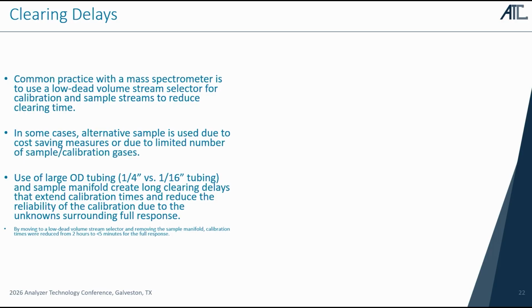In this particular installation, the integration team selected large outer diameter tubing of 1/4 inch versus standard 1/16 inch tubing recommendations, and a sample manifold that created long clearing delays and extended calibration times. We estimate that there was about 18 feet of 1/4 inch tubing that was all connected, so a very large manifold that took a very long time to clear out, increasing those clearing times.